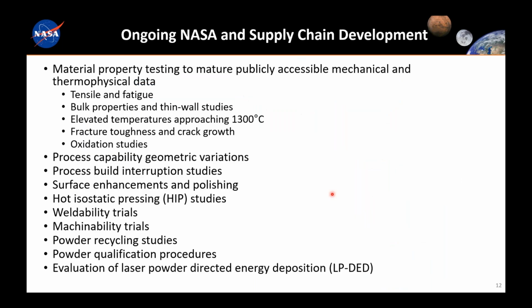Tim provided a little bit of an overview on where we're going with some of the material developments, and I just wanted to iterate a little bit more on this. We will be releasing a lot of data publicly on the material properties. This includes both tensile and fatigue, and the creep data that Tim mentioned. And one thing that's been important for us to mature this alloy is to understand both the bulk properties and thin wall properties. So we're completing those studies, and we'll be, again, releasing that data very soon. The elevated temperatures approaching 1300 C that Tim mentioned earlier, the fracture toughness and crack growth, as well as oxidation studies are in work.